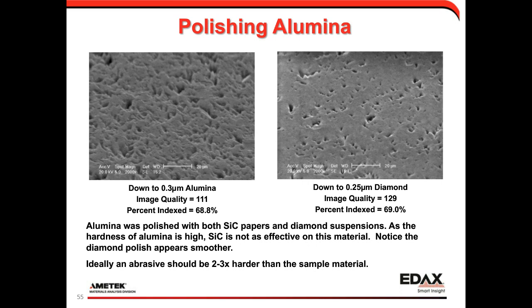If we compare those images, we see that, sure enough, it is a little bit flatter with diamond. But what's interesting is that while the image quality is a little bit better using diamond, the percent indexed is still about 69% for both. I think that's partly due to the fact that it's a generally brittle material, and even though it's not flat, we're still getting indexable diffraction patterns about the same percentage of the time after this polishing step. Ideally, the rule of thumb is that an abrasive should be 2 to 3 times harder than the sample material. Obviously, for something like alumina or polishing diamond, that option may not be available.